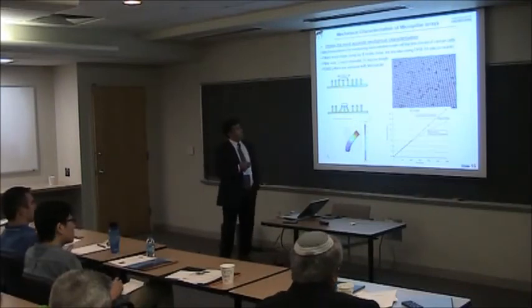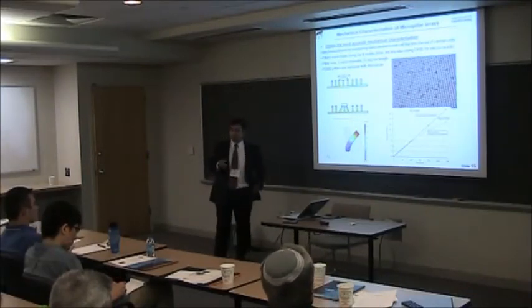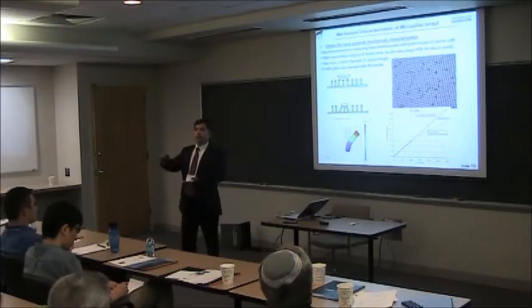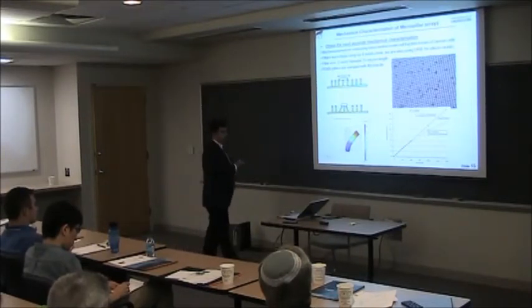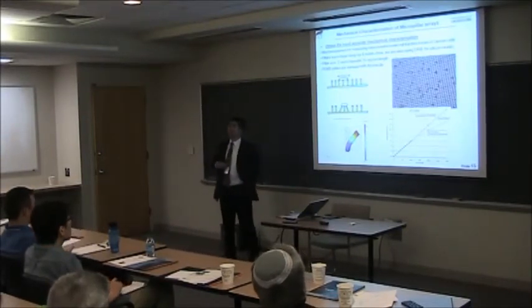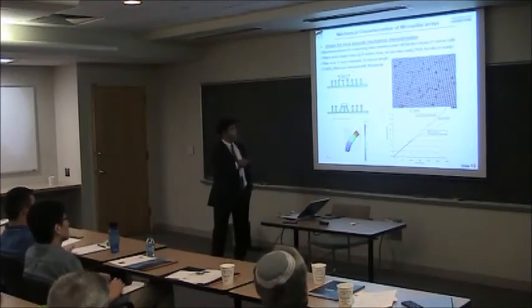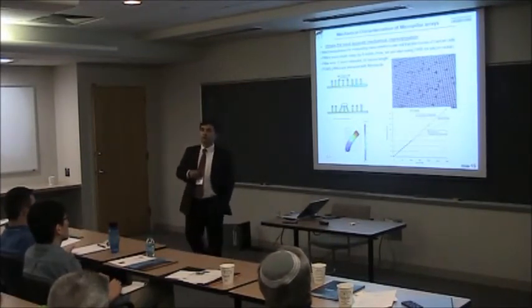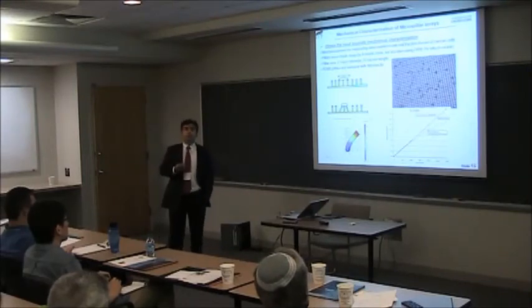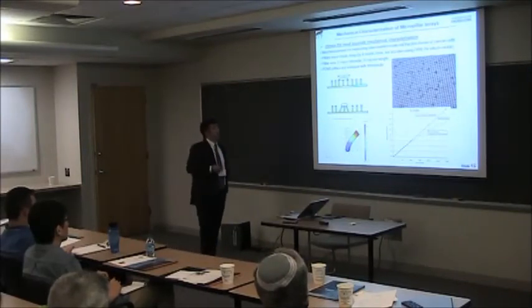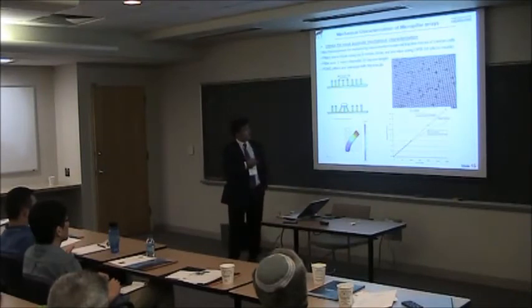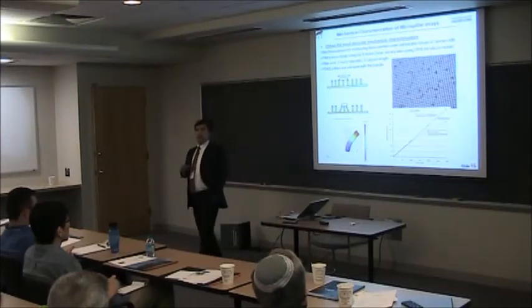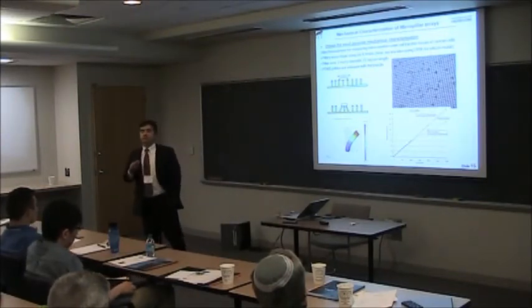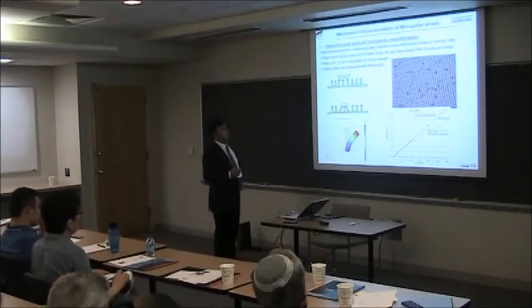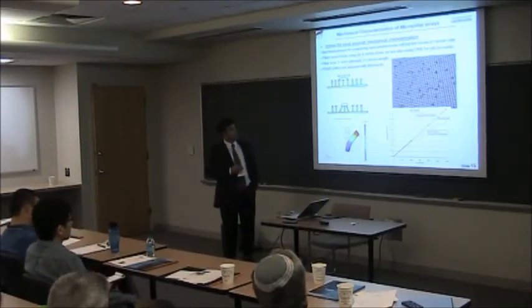But what we do is simply we created SU8 molds, and then we pressed PDMS on it and created these PDMS pillars. On top of the PDMS pillars, we are putting fibronectin, which is the material where the cells actually get food so that they can grow and move around. As they move around, they pull these pillars, and the displacement that they create will tell us the actual forces that they create during their motion.